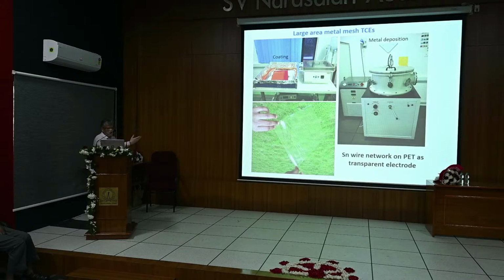And we have a couple of bars bought several years ago, and they are still in the lab. You can go on using. And this is covered with invisible mesh of tin wire. And you can achieve sheet resistance. We don't normally talk about resistance, we talk about sheet resistance. It is of the order of around anywhere between 10 to 100 ohm per square. Okay? These are tin wires. Very flexible. Now the plastic sheet is made electrically conducting.